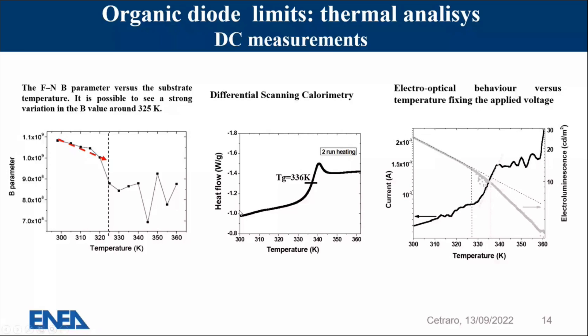This curve is almost similar to what we see with differential scanning calorimetry. If we instead go at a precise current, we can see that first the optical failure appears almost at the beginning of the transition zone, and then the electrical failure only definitely after the Tg and at the end of the region. And you can see that it is described perfectly by the differential scanning calorimetry measurements.